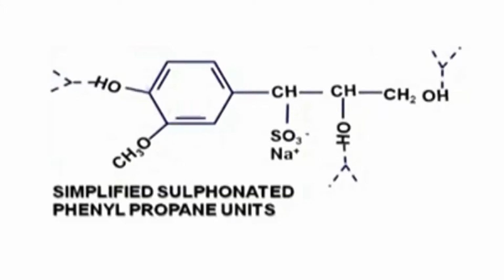Now, we are going to discuss the plasticizers. What are the lignosulfonates? What is the structure of the lignosulfonates? What is the molecular weight? Those things we will be discussing. Now I will show you the structure of lignosulfonates. This is the structure of lignosulfonates, with SO3 minus and Na plus groups. It is a polymer, that is, the structure repeats for n number of units. All these plasticizers and superplasticizers are of polymer type. In lignosulfonates, that is in plasticizers, the polymer structure will be a heavily cross-linked microgel.